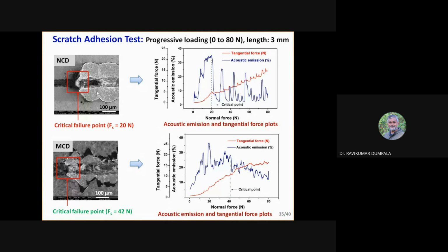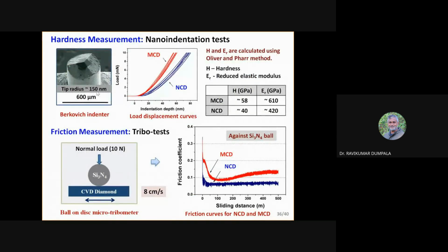So how we design the duplex coatings depends upon the properties. From this, what we can see is that on the surface you want microcrystalline diamond, because it is sticking well to the surface. But look at the next property, friction, at the right bottom. On the y-axis you have the friction coefficient, the x-axis is sliding distance. It's very clear that the friction coefficient is very low for nanocrystalline diamond, which you want on the top of the surface. So you want microcrystalline diamond at the substrate and nanocrystalline diamond above it, so that you have better adhesion and better friction properties.